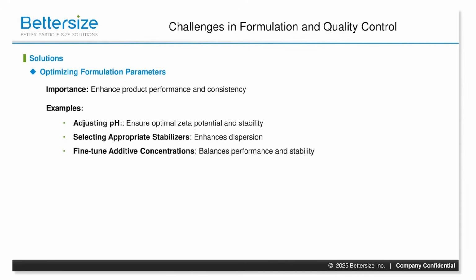Solutions to common challenges include optimizing formulation parameters. The importance of this is that it enhances product performance and consistency by fine-tuning the composition and processing conditions. One example would be to adjust the pH, which, as we have mentioned, ensures optimal zeta potential and resulting stability. And this prevents issues like agglomeration and sedimentation. By selecting the appropriate stabilizers, this can enhance the dispersion and prevent aggregation.